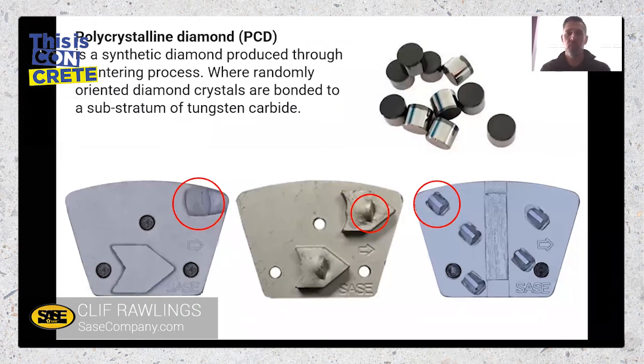So when a typical metal bond won't do it, PCD or polycrystalline diamond type tools are probably your best option. That's the most aggressive option too. So what I try to do in this slide is show you basically what PCD is. It's polycrystalline diamond, synthetic diamond produced through a sintering process where randomly oriented diamond crystals are bonded to a substrate of tungsten carbide.